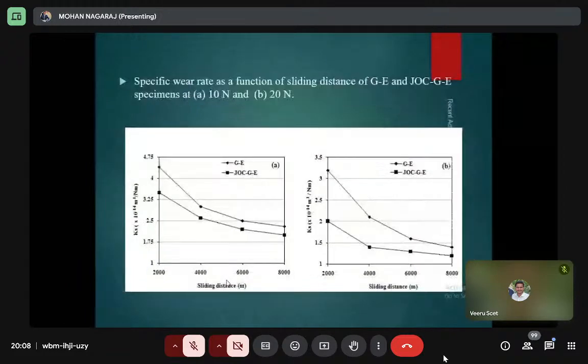We studied these materials at the sliding distance. This is the specific wear rate. There is a drastic reduction of the materials taking place, and then a linear reduction will be observed from 4,000 to 8,000 meters. Why do we observe the drastic reduction in both the materials? There is the softening nature of the epoxy materials initially.